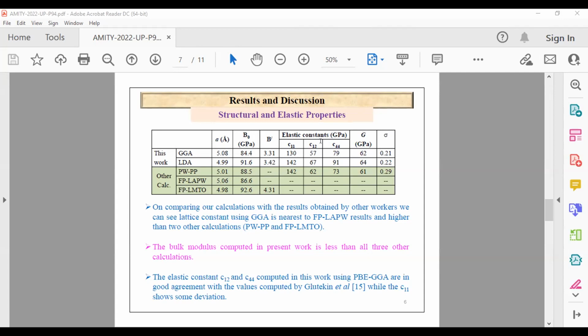Now we also computed the elastic constants for the system, and we only find one study earlier performed for this system, and we can compare our results with that earlier study. We see that our calculated values of elastic constants using LDA type calculations for C11 and C12 are near the PWPP method calculation, while our GGA value of C44 and shear modulus is near the PWPP calculation.